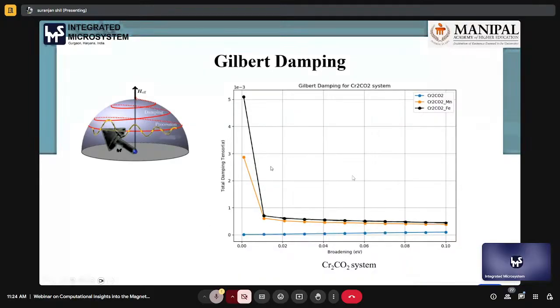So here we are not getting that stable a configuration, but in future we can dope with such an atom that it can get more stabilized and the curve becomes linear. So we actually need a linear curve for the stability of the magnetic property. But here none is that stable. Without doping, it is quite a little stable compared to the doped one. So that means the doping destabilizes the magnetic state compared to the undoped one.